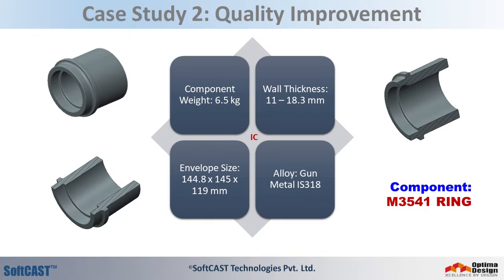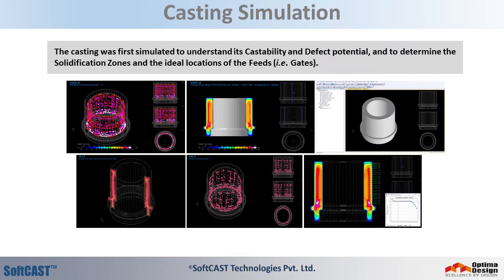Our second case study is a quality improvement project for a 6.5 kg gunmetal ring casting. This was at a medium-sized IC unit in Western India. The results of the casting simulation, the first step generally performed, that is hotspots, temperature maps and thermal traces, clearly showed the defect potential, the solidification zones, and the required locations of gates.